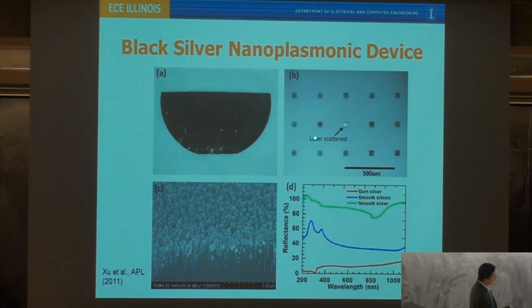And if you shine a laser spot on the other areas outside the squares, you're going to have much lower scattering intensity. The reason why we call it black silver is because it really looks black, even though it has a very thick silver layer deposited on the surface.